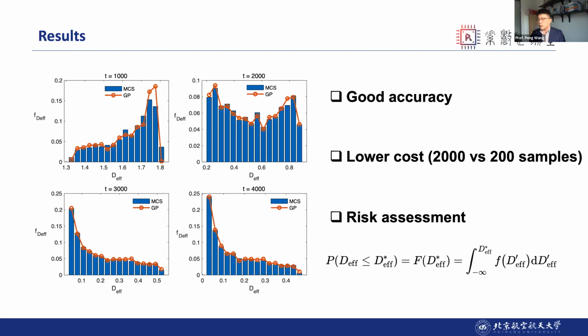And as we can see, at all these 4 time steps, there's a good match between the prediction and these Monte Carlo simulations. But we're at a much lower cost because we only use 200 samples to build this surrogate model between local structure and the overall diffusion coefficients. And actually, with this probabilistic density function, one can conduct risk assessment, which by definition is the integration of the PDF over specific values.